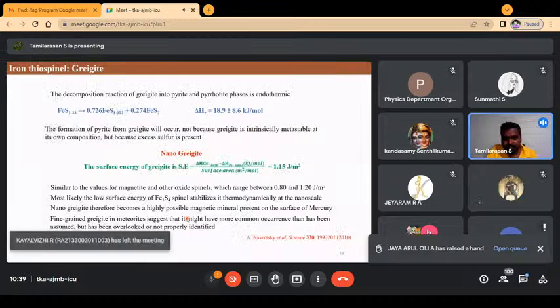So we take the difference and divide by the surface area of the nanomaterial, and you get surface energy, which is measured by experiment. No matter what the particle size is, you can measure surface energy. We determined the surface energy of nanogreigite for the first time, and it's around 1.15, which is similar to nano magnetite and other spinels, which is not surprising, but still we measured it.